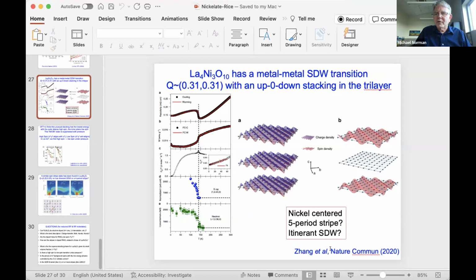That is, the charge wave vector is twice the spin wave vector. And for the available L-dependence, we have extensive L-dependent data. It looks like the CDW exists on all three planes, whereas the spin density wave only exists on the outer plane. This is not surprising from cuprates. You see this in cuprates when you have tri-layer or four-layer or five-layer materials. Inner planes and outer planes behave differently.